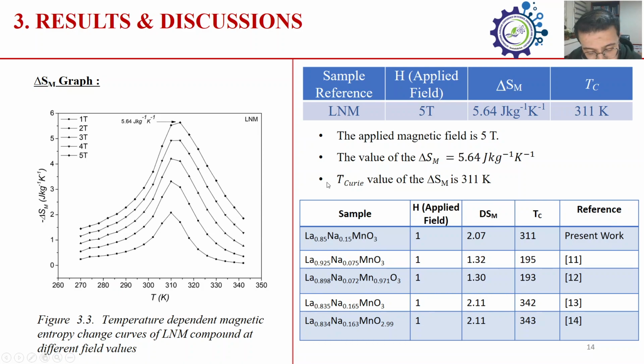You can see the magnetic entropy change graph on the left hand side, and the details are given in the table. When we compare with the literature, it is clearly seen that we obtain a Curie temperature value near room temperature and a high delta SM value.